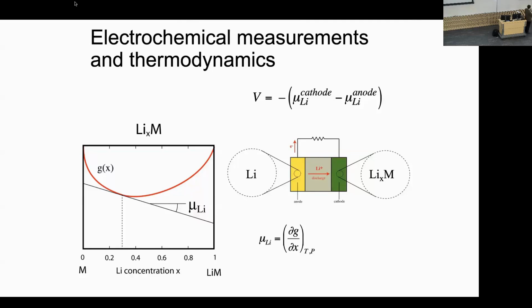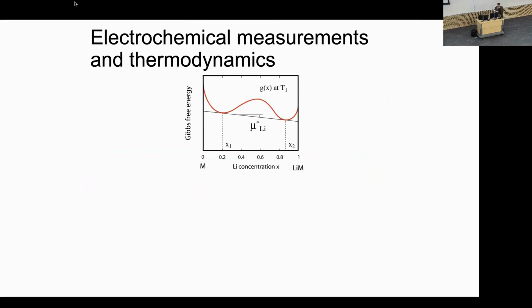And so the chemical potential itself is really the derivative of a Gibbs free energy. So what you're really measuring is the derivative of the Gibbs free energy. So if you integrate the voltage, you essentially can reconstruct the free energy of your material. So when you're actually using your battery, you're measuring the voltage and the chemical potential of your elements. And this has interesting consequences.